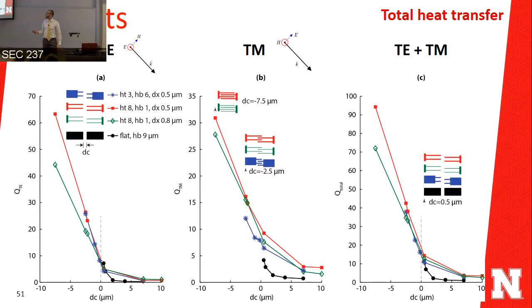That's why the flat surface has higher heat transfer than the structured surface. Also, if you see here, the heat transfer of the 8 micron and 3 micron tooth height are almost the same. If you turn on the TM wave, it's completely different. The heat transfer is higher than the flat surface because the resonant modes participate in the heat transfer. And you can notice that there is not much difference between the 2 cases of the teeth with different separation gaps, 0.5 micron separation and 0.8 micron.